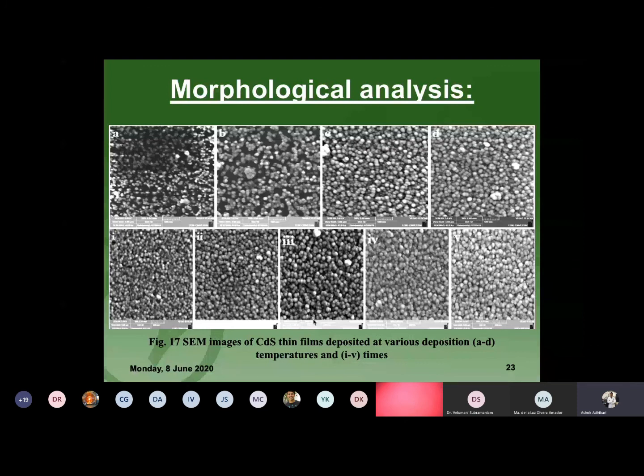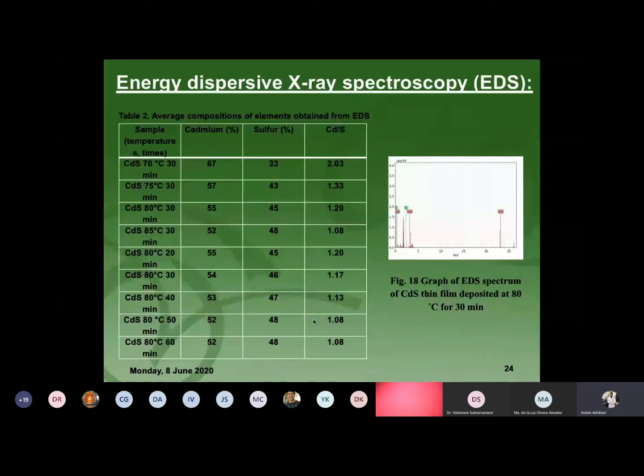The grain size we obtained is around 10 to 30 nanometers. For the average composition of the elements cadmium and sulfur, we performed EDS.